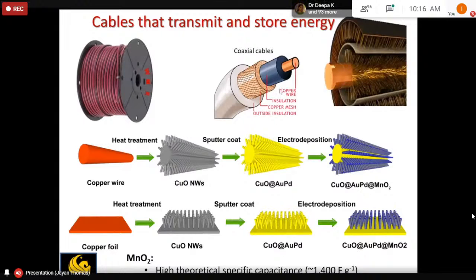What we did is we took this copper cable and made nanostructures on the surface, which is a simple procedure. When copper is heated to a higher temperature, you can see the formation of copper oxide nanowhiskers on the surface. And then we made that into a supercapacitor, wrapped with another filament with these types of nanostructures.